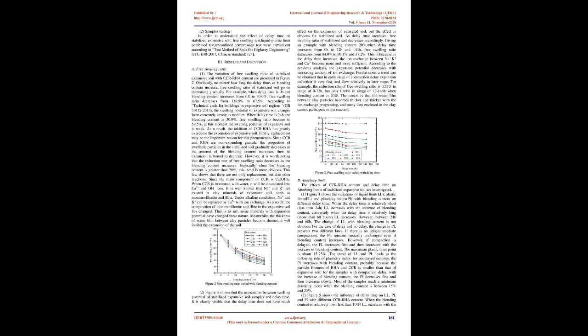Obviously, no matter how long the delay time, as blending content increases, free swelling ratio of stabilized soil goes on decreasing gradually. For example, when delay time is 0h and blending content increases from 0.0 to 30%, free swelling ratio decreases from 138.5% to 67.5%. According to the Technical Code for Buildings in Expansive Soil Regions, GB 50112-2013, the swelling potential of expansive soil changes from extremely strong to medium. When delay time is 24h and blending content is 30%, free swelling ratio becomes 59.5%, at which point the swelling potential of expansive soil is weak. As a result, the addition of CCR-RHA has greatly overcome the expansion of expansive soil.